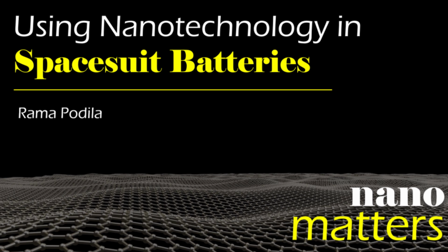So you can reduce the weight, that is, you can pack more energy per gram of material if you use silicon. But the problem with silicon is that when lithium ions go into silicon, it just expands and then it bursts open, and then the entire material gets pulverized, which is a big problem for having stable batteries.